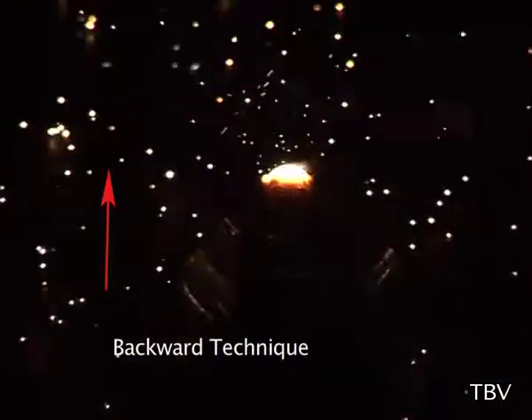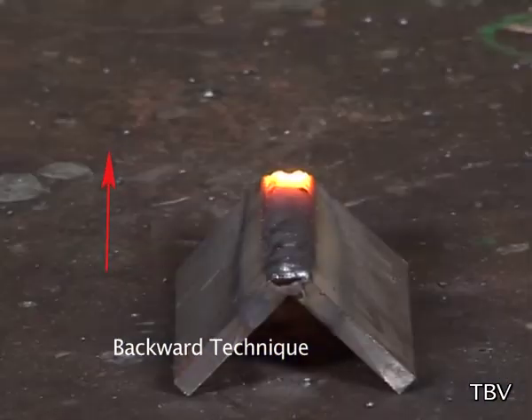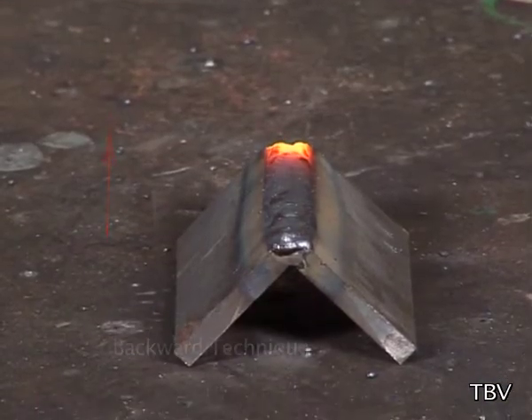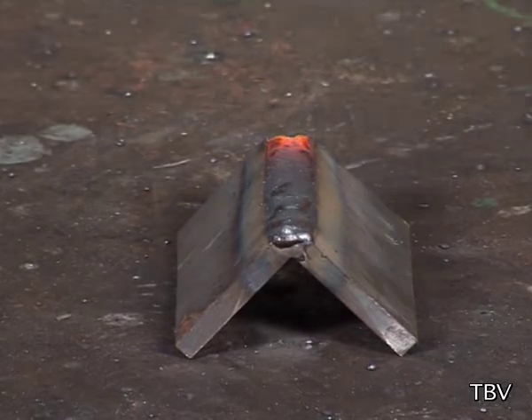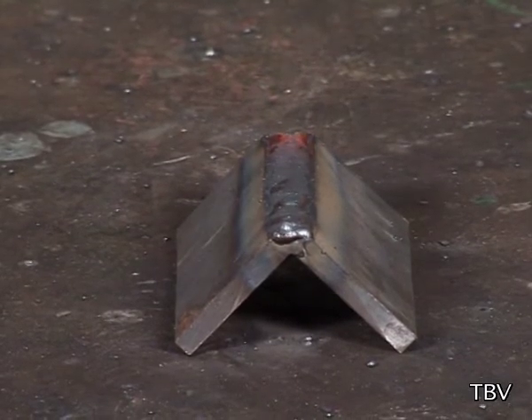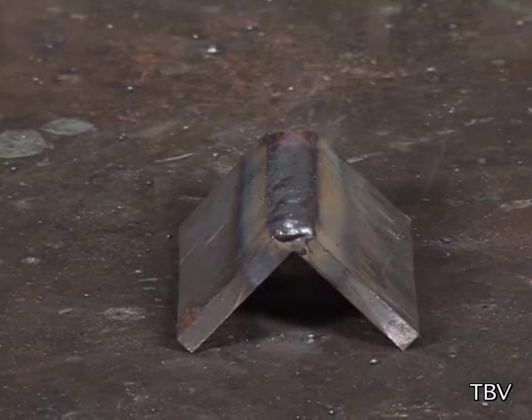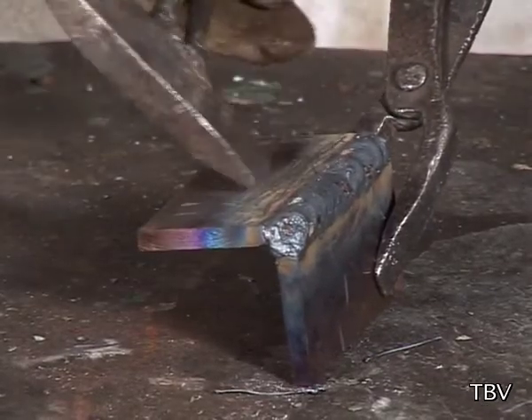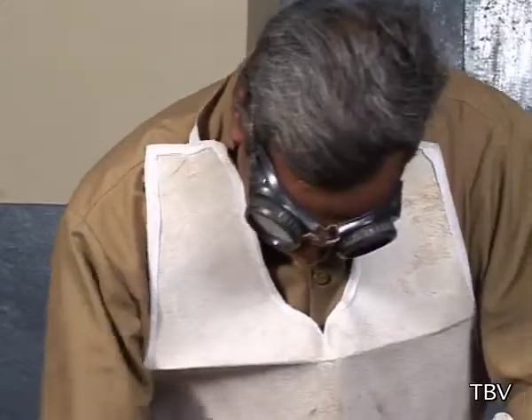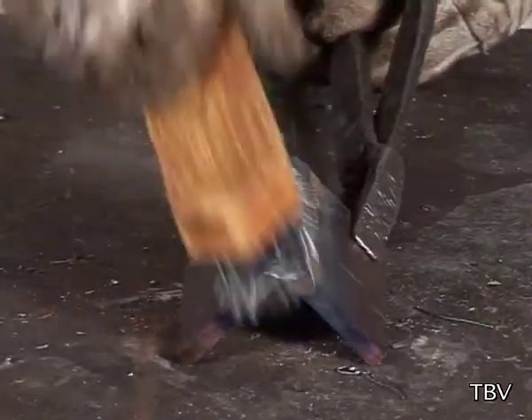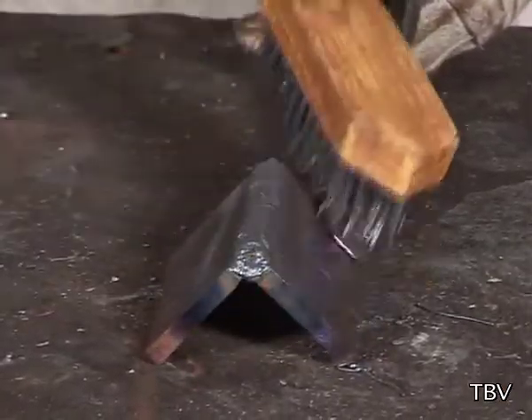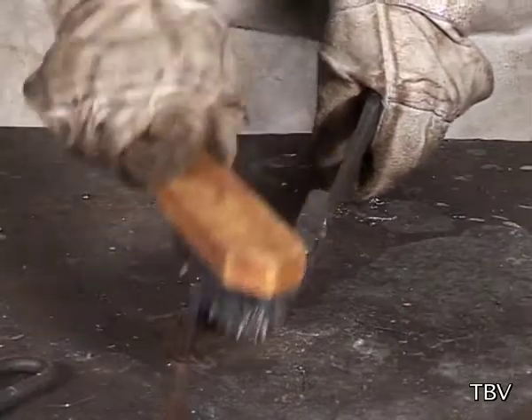Maintain a filler wire stick out of 8 to 10 mm from the end of the contact tip to the job as required for dip transfer mode. As seen in the earlier exercise, let it cool for 5 to 10 minutes. Remove spatters with a chipping hammer and clean the joint using a steel wire brush as done in the previous exercises. Check the welded area for uniform flow of filler material.